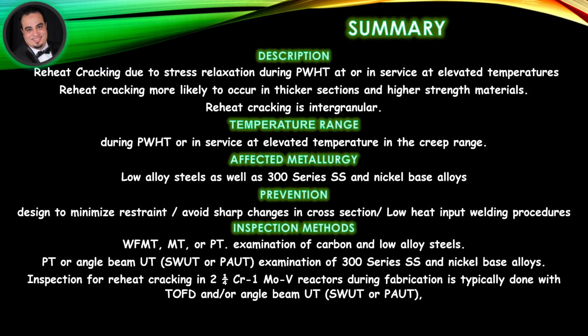Summary. Description. Reheat cracking due to stress relaxation during post-weld heat treatment or in service at elevated temperatures. Reheat cracking is more likely to occur in thicker sections and higher strength materials. Reheat cracking is intergranular. Temperature range: during PWHT or in service at elevated temperature, in the creep range. Affected metallurgy: low alloy steels as well as 300 series stainless steel and nickel base alloys.